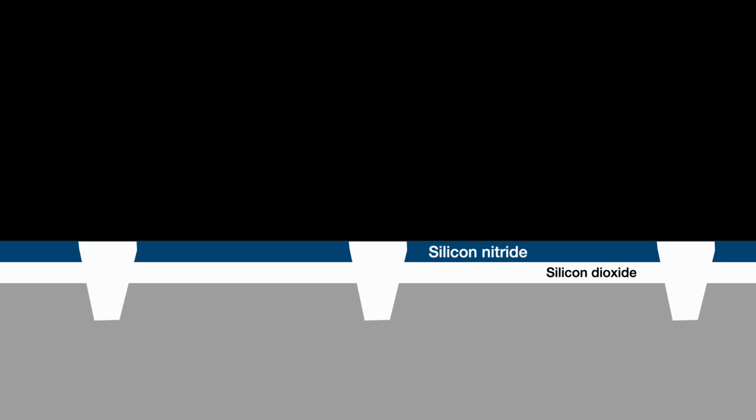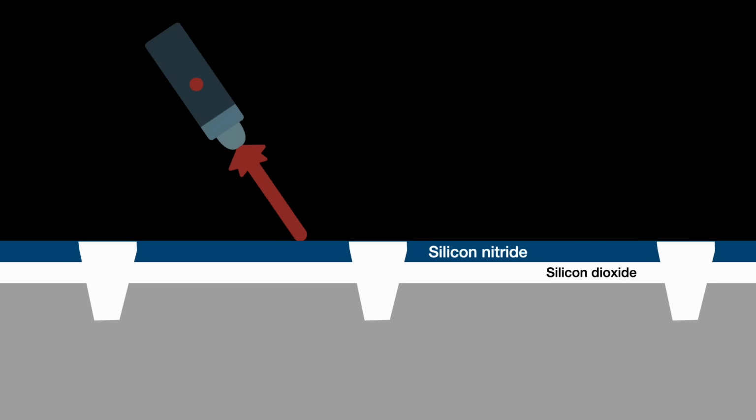Now, remember all the way at the start of this STI flow when we applied a stopping layer of silicon nitride and I said it was going to be useful later? Now it is finally coming into play. It's critical to know exactly when to stop the CMP polish lest we grind too deep. So a laser is shone onto the wafer surface during the polishing, sensing for when we finally expose the silicon nitride, our stopping layer. I love plot payoffs like this.